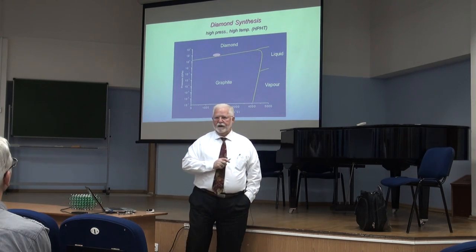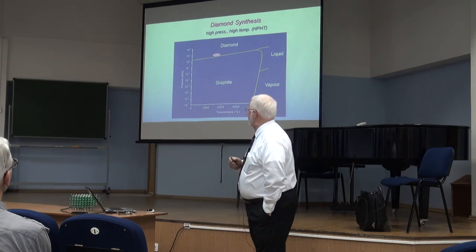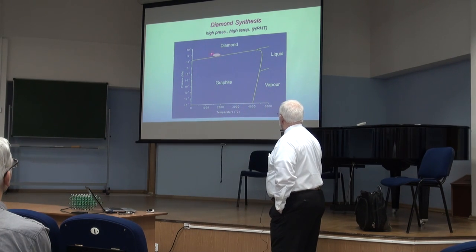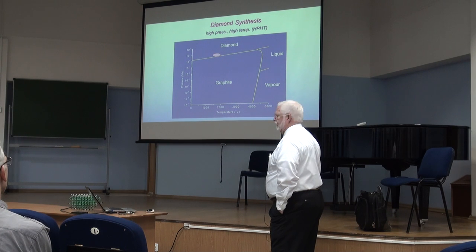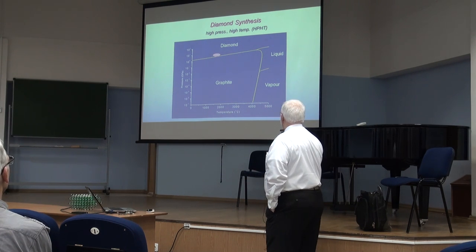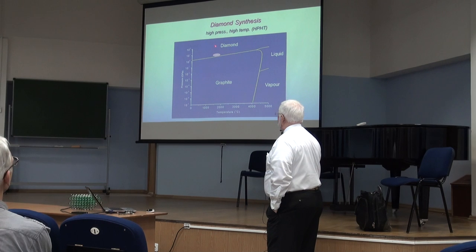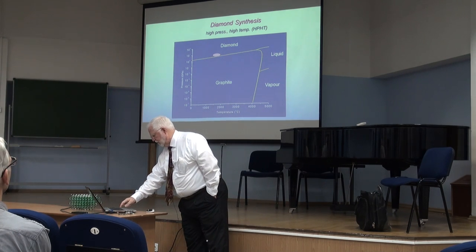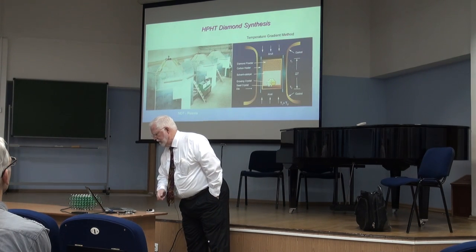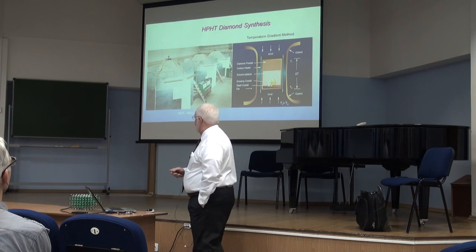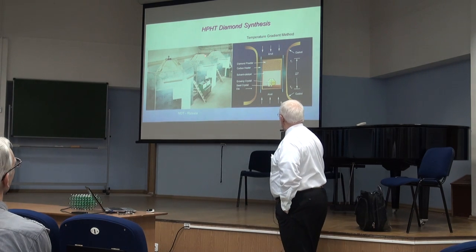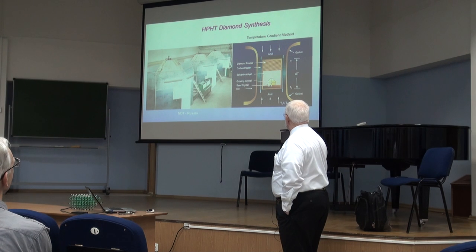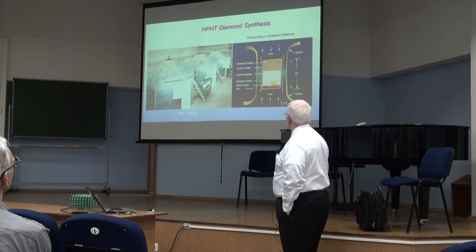So now let's turn to high pressure, high temperature synthesis. This occurs at a slightly higher temperature, again where diamond is stable, and uses a metal catalyst that dissolves carbon to help it grow. This technology was developed over 60 years ago, and here's an example of some high-pressure presses that were recently installed at New Diamond Technologies outside of St. Petersburg. You can see the scale of this. A person would be about this size.